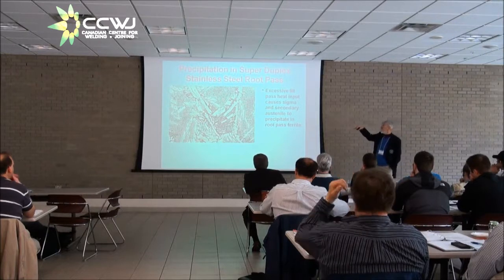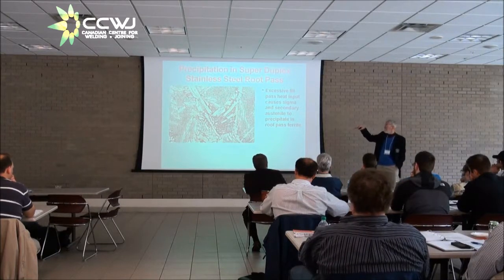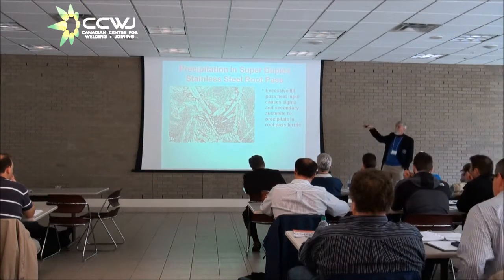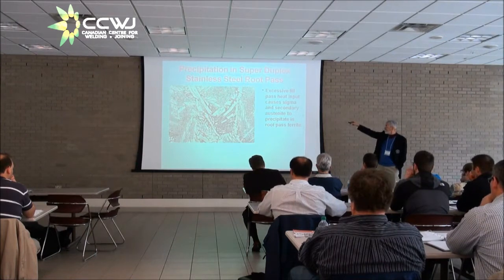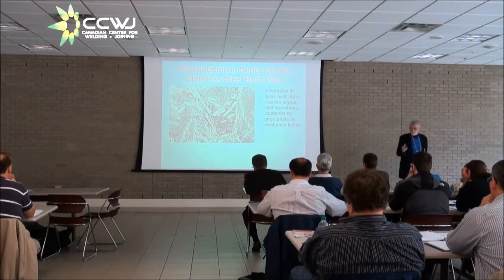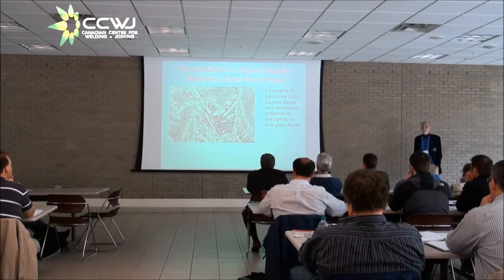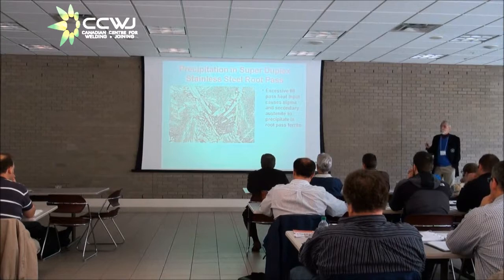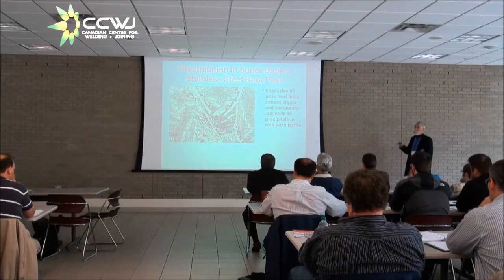root pass solidified fast enough that some nitrogen was held in solution in the ferrite. Maybe it was even some cold nitrogen, we don't know. But the hot pass reheated it and caused secondary austenite to precipitate and sigma. It's pretty hard to tell which is the secondary austenite and which is the sigma phase in the center of those high ferrite areas. But that's a mixture of secondary austenite and sigma phase. So the right way to do things is to have the heat input of the root pass be at least as high as the heat input for the second pass.